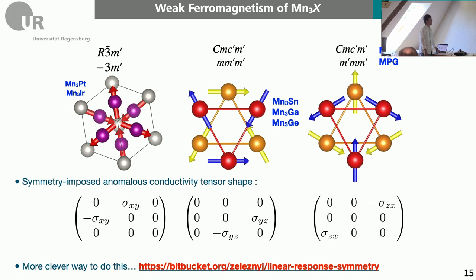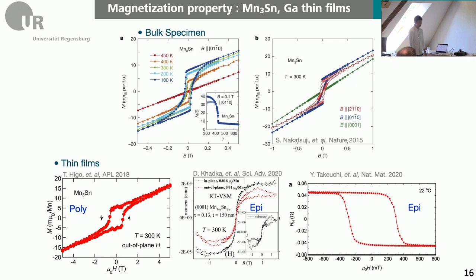We found it curious that not all reports on thin-film manganese-3 systems reported full magnetization properties. They just showed room temperature data, or sometimes not very clear magnetization. Also, somehow epitaxially grown films showed really high coercivity compared to the bulk material. The bulk coercivity is below about 100 oersteds, but here it was more than 20 times larger. So there is something going on.